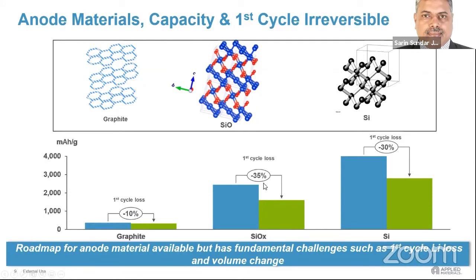And SiOx batteries are again 35%, and silicon it is say close to 30%. And one of the technologies that we have developed, called pre-lithiation, for depositing lithium on the graphite and graphite-silicon anodes, can completely eliminate this loss, bring back that 30% capacity that has been lost. That is something that we will show.